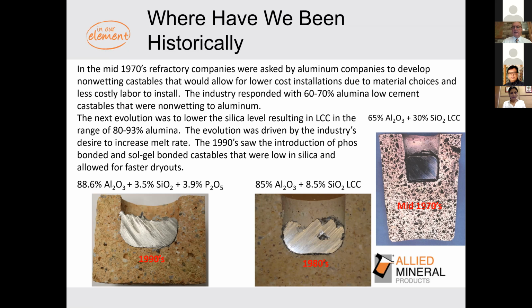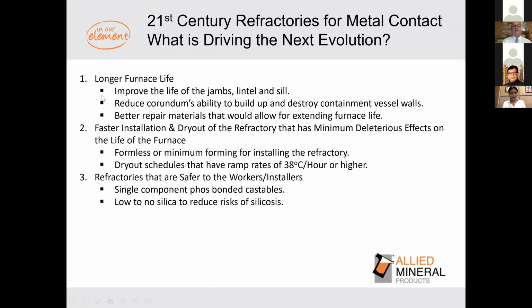So the industry was wanting, again, materials that could extend the life of the furnace. And in the destruction of an aluminum furnace, you have things such as mechanical abuse in the jambs, lintel, and sill. You have the corundum and its ability to destroy the refractory, as you saw in the first pictures on the first slide. And in order to improve the furnace life, we needed to develop better repair materials. So you didn't always have to tear out all the refractory back to the shell and build it back with new materials. Was there a way that we could just clean any penetrated material away and then build back the thickness of the walls and floors without having to tear everything out?